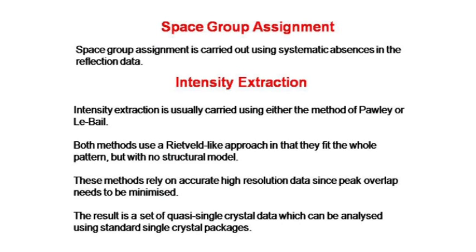Space group assignment, just like we did the other day, uses systematic absences. So you just do that like you do for single crystal. Intensity extraction, we usually carry it out using the Pawley method or the Le Bail method. GSAS, which is the program that we tend to use, uses the Le Bail method, and that's quite good actually in GSAS. It works very well.